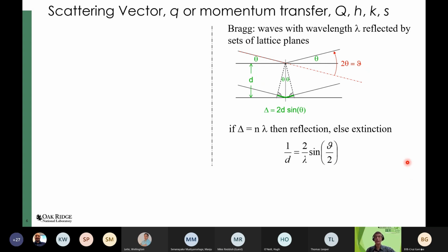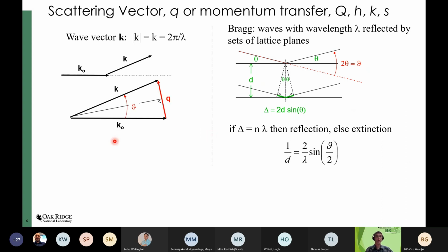Now, if you have smaller crystals, that destructive interference is not perfect, and you'll get some broadening. From the broadening, you can then get crystallite sizes. You might be familiar with that as well. Small angle scattering is very similar to that, in that you're also getting size information, except we don't need a crystal lattice to begin with. But I'm going to go back to how we normally get to the scattering vector Q, how this is typically handled in the scattering lecture.